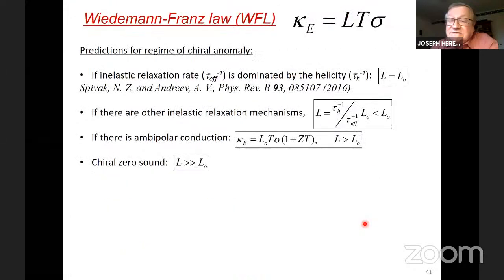So the prediction from that theory is that if the inelastic relaxation rate is related to the helicity, to the inter-Weyl point scattering, then we expect L equals L naught. If there are other inelastic relaxation mechanisms, of course, we would expect L to be smaller than L naught. Ambipolar conduction, I have supplemental slides you can ask about, but if that were the case, then we would have L larger than L naught. There is another theory, chiral zero sound, which also predicts L much larger than L naught. I'm not going into theories, I'm just going to show you the experiments.